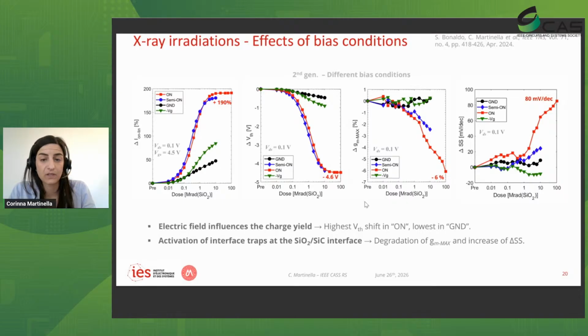So we also saw a degradation of the transconductance here, indicating the generation of interface traps that cause a degradation of the transconductance of the device and an increase of the subthreshold swing.